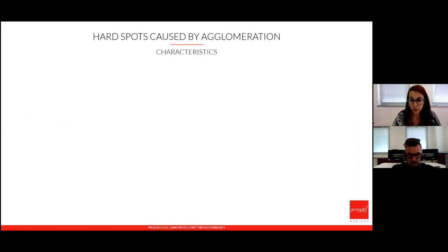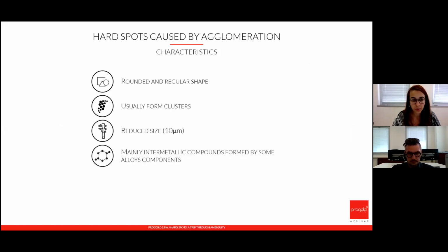The second case I'm going to talk about, which is the second macro category, is hard spots caused by agglomeration. In this case, they tend to be regular and rounded. They are made up basically from elements that are already inside the alloy and tend to be very small, but they appear in clusters, so the cluster area can be very big. And in this case, we can only have them when we reuse the metal.